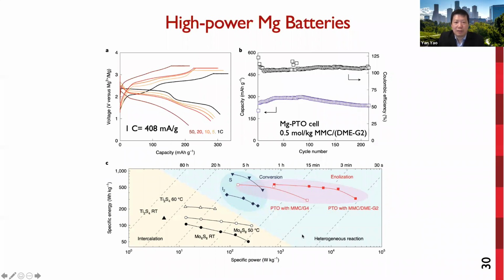So finally, we couple the PTO cathode and the new DME G2 electrolyte to yield a high power magnesium battery prototype. We have shown that at 20C and 50C, capacities of 200 and 210 can be retained. So stable cycling at 5C can be maintained over 200 cycles.